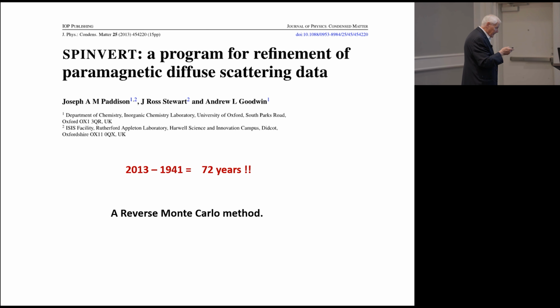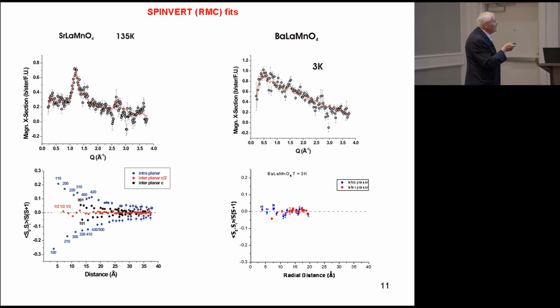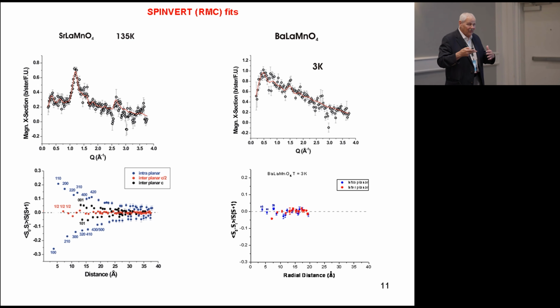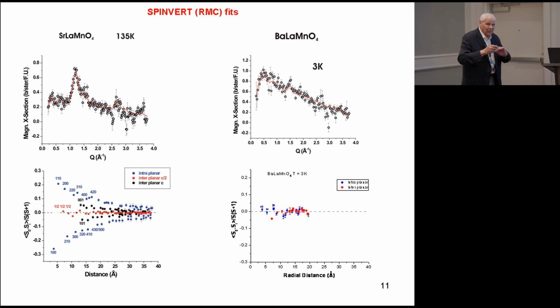Okay, so this is a reverse Monte Carlo technique, which is very popular these days. And here are some fits that we've done to the data. Here we have this strontium lanthanum manganese compound, the all-strontium phase, above the Néel temperature, and you can see a perfect Warren line shape. But this is not using Warren's formula; it's using the reverse Monte Carlo method, and so it's model independent.